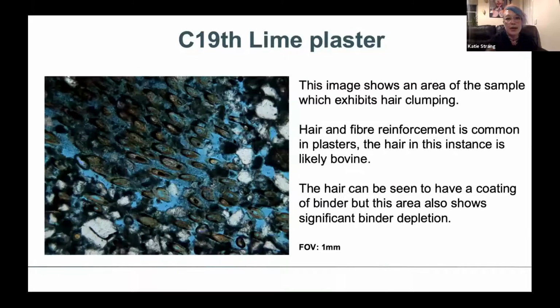This is an image of the hair actually, yes. So this is a bit where you've got hair clumping, which is very bad. You want your hair, or your fibres, to be distributed evenly throughout your material and not clumped into one place. So even though there is some binder around these particles, around this hair, there's still a lot of porosity there, and that area will be significantly weakened because of that clumping of the hair.